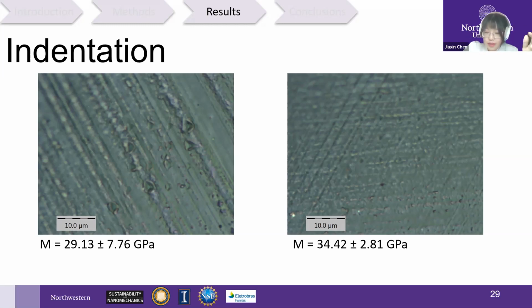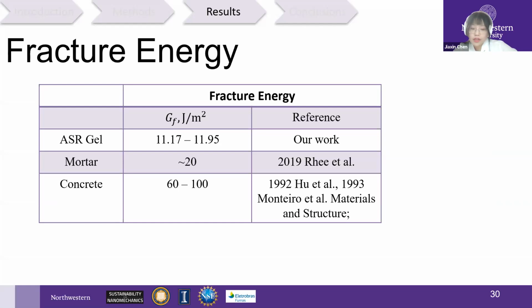Therefore, from this perspective, our measurements of Young's modulus agree with other measurements of the ASR gel crystals. After obtaining fracture toughness and elastic modulus using the Griffith-Irwin formula, we can obtain the fracture energy. For our ASR gel crystals, we have a fracture energy of 11.17, and also 11.95 for the other specimen.